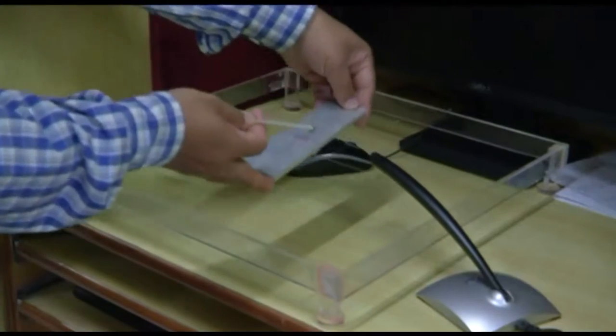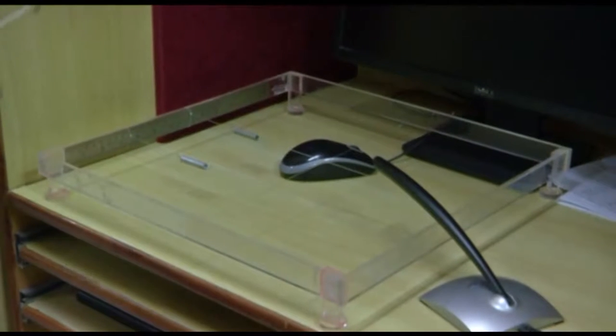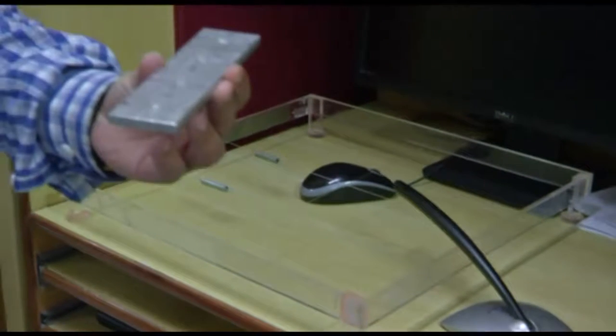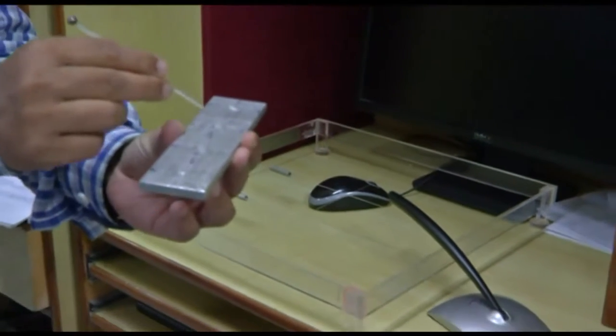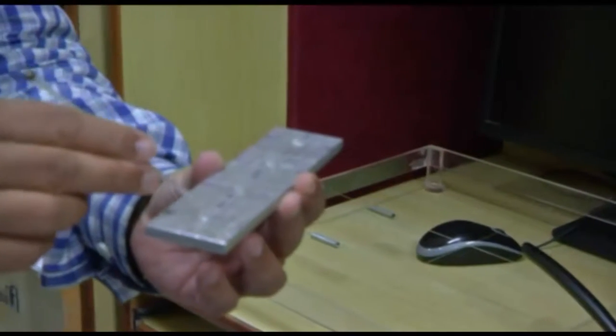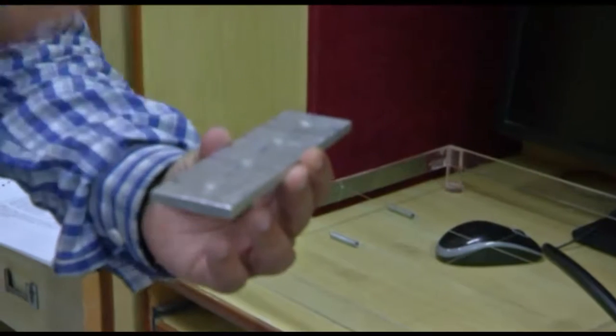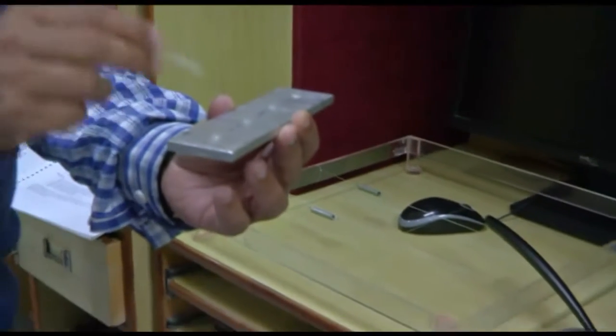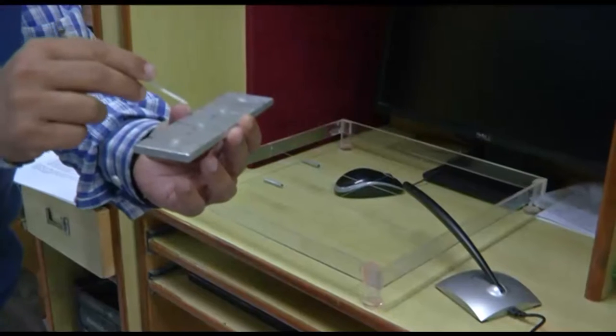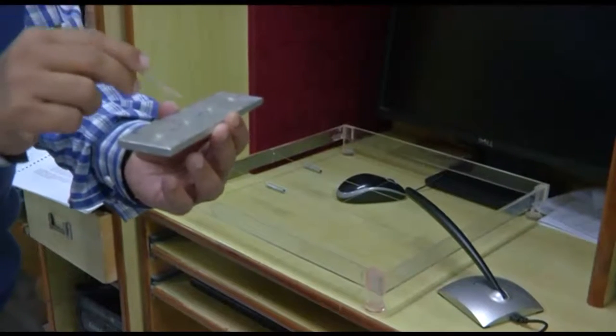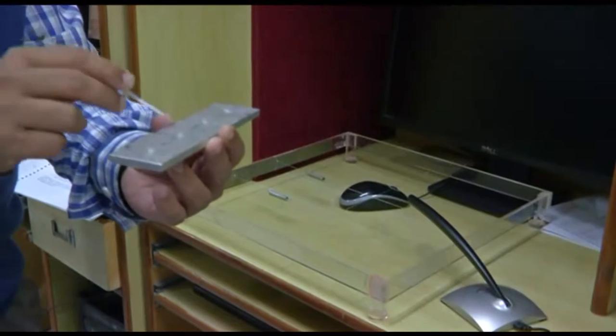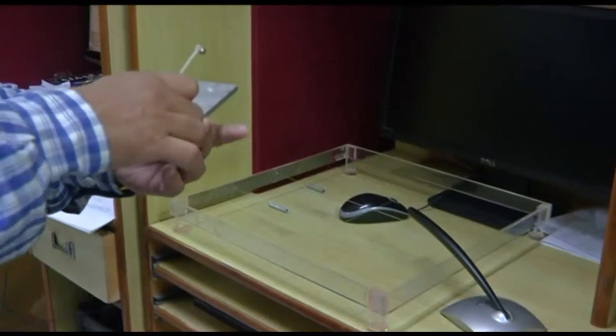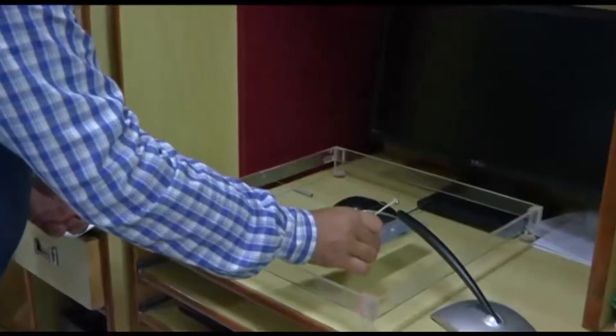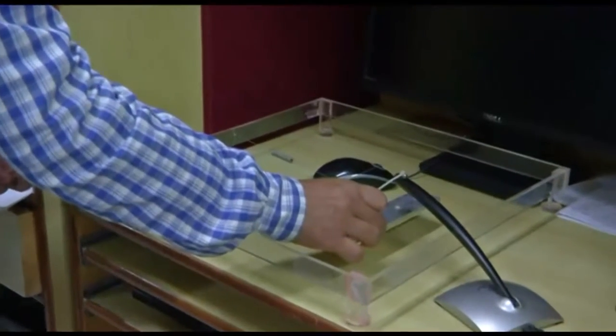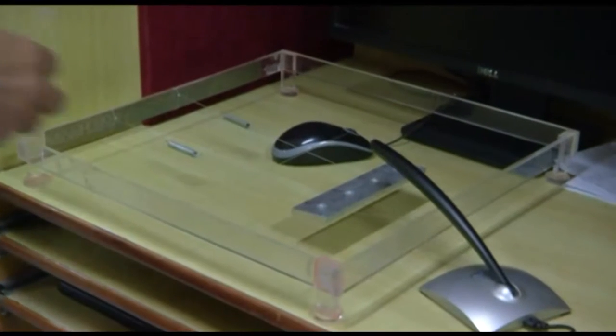Now, we are going to replace this solid aluminium bar by another aluminium bar, and you should look at it very carefully: this aluminium bar has small holes here. These are not through holes; the hole is made only up to a certain level, because at the top level there would be further stress concentration in the system. These small holes we have filled with viscoelastic material, and we are going to put it in the same region here and carry out the same experiment with this system.